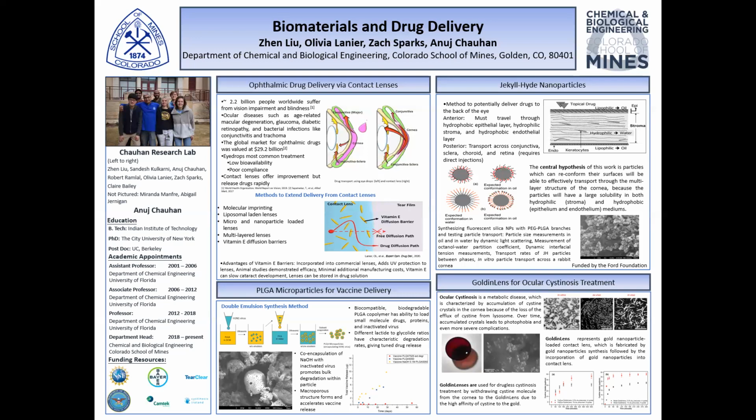An interesting method that's been used is the in situ formation of gold nanoparticles in silicone hydrogel contact lenses. In the bottom right, we see ex vivo results from the uptake of cystine by the GoldinLens. Different GoldinLens fabrications were used, and we see that there's a higher cystine uptake for GoldinLens with a higher concentration of gold precursor solution.